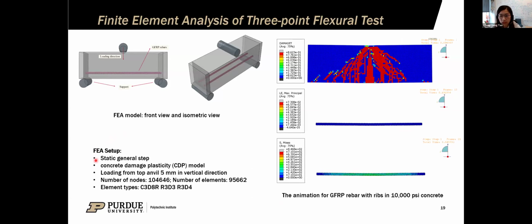And we also use different element types in the finite element models to describe the rebar ribs and its surrounding areas. From the finite element simulation, we could get a crack pattern like here, showing the animation using the parameter called damage T. Damage T is short for damage tension. So the animation shows the finite element result for the flexure test, damage T on concrete, and also the stress on rebars over time.